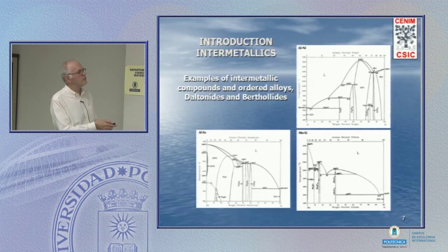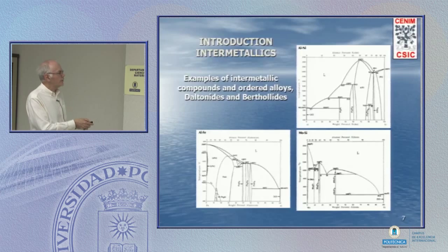Here's the nickel end, solid solution nickel. Here's the Ni3Al intermetallic. You see it exists over a fairly narrow composition range and is ordered all the way up to melting. Here's another compound, the NiAl. It's got a different chemical structure, a different phase. It's ordered over a fairly wide composition range, again all the way up to the melting point. It's very strongly ordered.